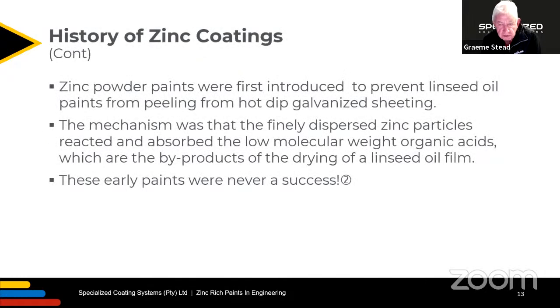Zinc powder paints were first introduced to prevent linseed oil paints from peeling from hot dip galvanized sheeting. The mechanism was the finely dispersed zinc particles reacted and absorbed the low molecular weight organic acids, which are the byproducts of the drying of the linseed oil film. These early paints were never a success.